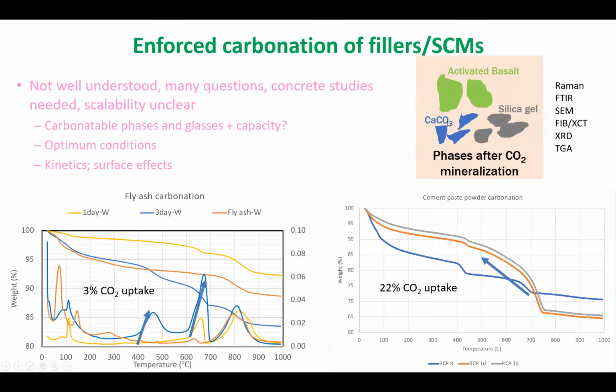So how does this look? If you take a fly ash - this is basically the fly ash at 1 day, this is the fly ash at 3 days, and this is the fly ash with just the mixed water. Typically calcium carbonate decomposes at about 600 Celsius, though there's a lot of variation in that. You see that the original material already has maybe a little bit of a peak here - maybe it's an artifact, it's really very small, or maybe there's a little bit. And then at 1 day, this peak increases, as you can see here.